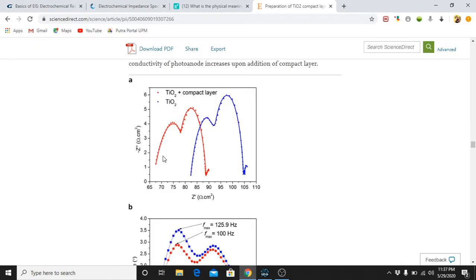So when we got the data like this, this is obviously a Nyquist plot. When we typically talk about solar energy, which is dye-sensitized solar cell, normally people will get two semicircles. The semicircle at high frequency here is the semicircle at the counter electrode electrolyte interface. At low frequency here is the semicircle of charge transfer resistance at the TiO2 dye electrolyte interface.